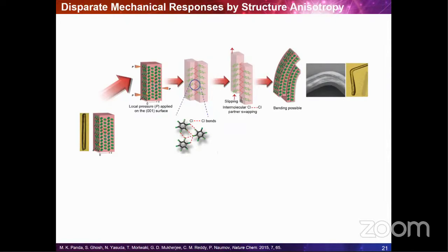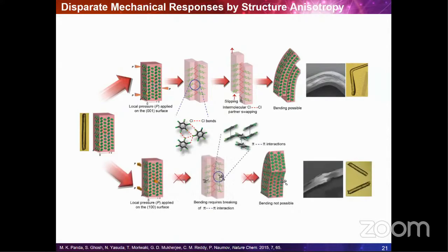The combined microscopic, spectroscopic, and diffraction analysis of the bent crystal basically showed that this preservation of crystal integrity when stress is applied, in this particular case on the 001 face, requires sliding of layers by breaking and reformation of halogen-halogen interactions or bonds. And this is where, again, the non-covalent interactions come into the picture. If you apply stress on the 100 face of the same material, in the direction where the pi-pi interactions dominate the packing, this leads to immediate crystal disintegration. So you can see that anisotropy of the crystal plays a critical role in how the crystal responds to mechanical stress, which is a very basic property, and we still do not understand it.